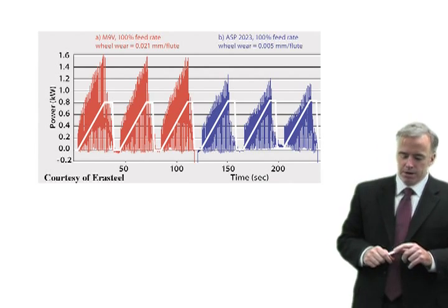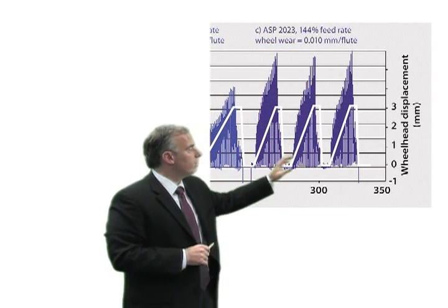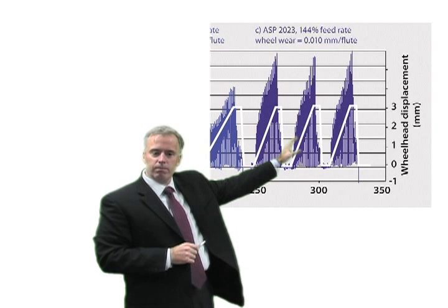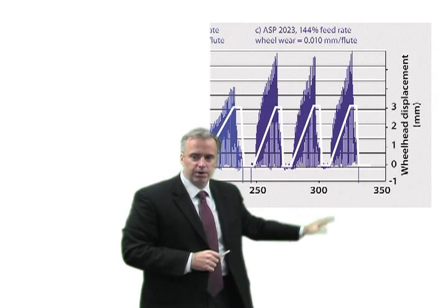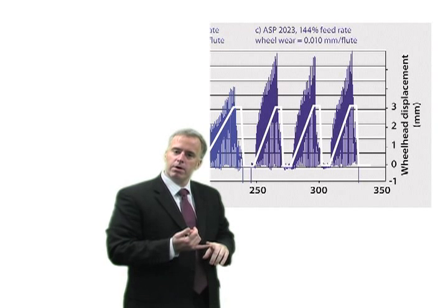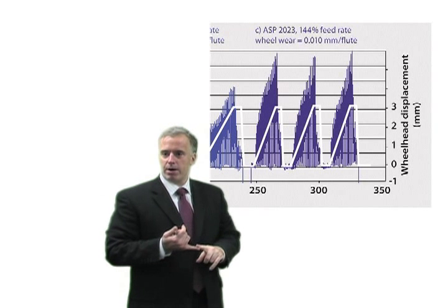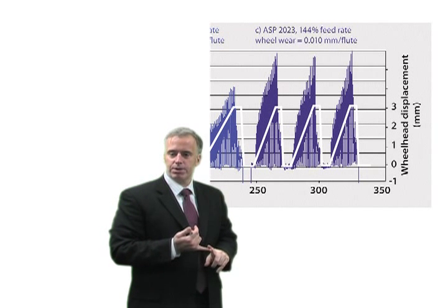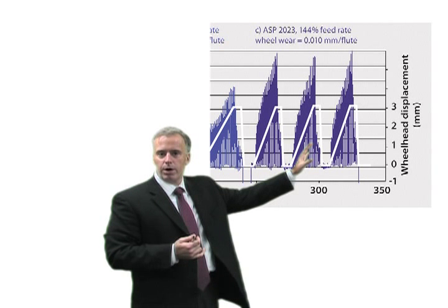So what we can do is we can increase our feed rate. Here, we increased our feed rate by 44%. We increased our feed rate, of course power goes up because we're removing more material in the same amount of time, wheel wear goes up.